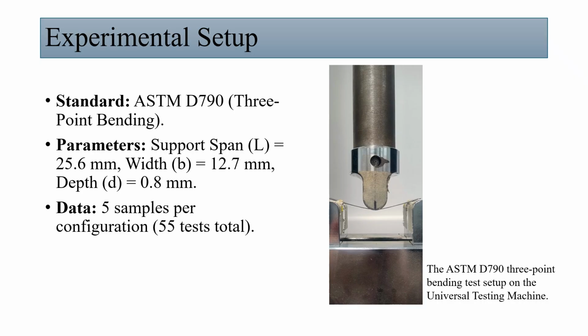For the mechanical evaluation, we followed the ASTM D790 protocol for 3-point bending tests. Based on our specimen thickness of 0.8 mm, we calculated the required support span to achieve an L/D ratio of 32. We tested 5 samples for each of the 11 configurations, totaling 55 tests, continuously recording the applied force and central deflection until failure. This provided a robust experimental baseline.